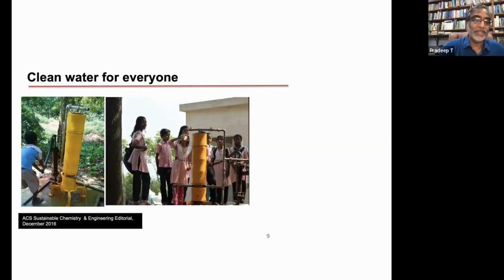When these materials were developed, when we found that they are effective in removing arsenic in two oxidation states, arsenic 3 plus and arsenic 5 plus in water, with not excessive contact time, we decided to apply it in the field. So here is a cast iron pump. This pump is operating in Nadia district in West Bengal. And in that particular region, if you take water from this pump, and that water is falling on this cement platform, what you see is red stain.